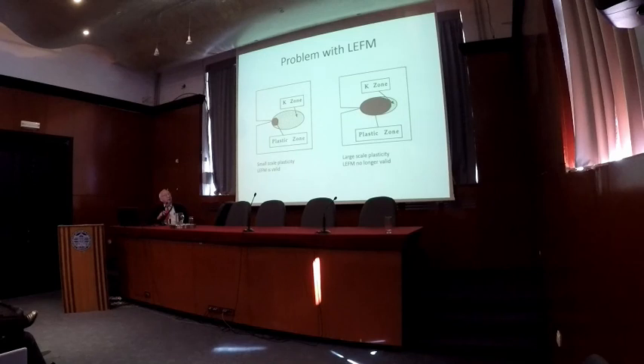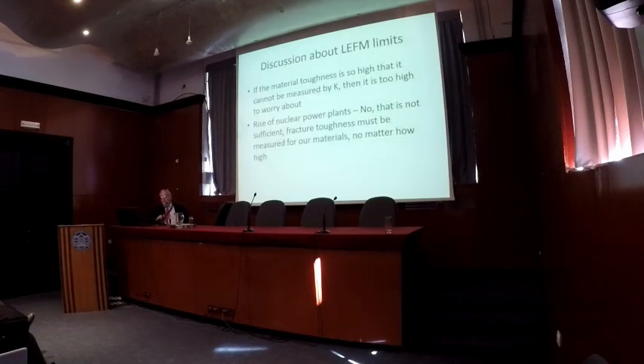Now, if you calculate plastic zone size, here's what happens. If it stays nice and small like this, and you have the K zone, which is really not a quantitative zone but an arm waving zone, but if you haven't wiped out the K zone, everything is fine. But if you have such a big plastic zone that the K zone is kind of wiped out, everything is not fine, and you should no longer be using linear elastic fracture mechanics.